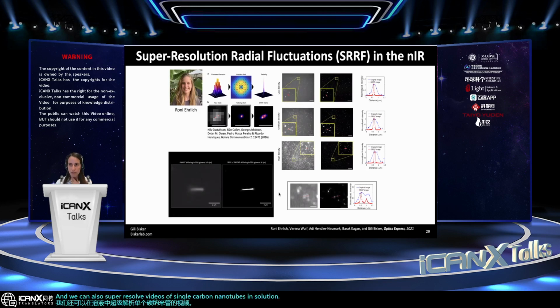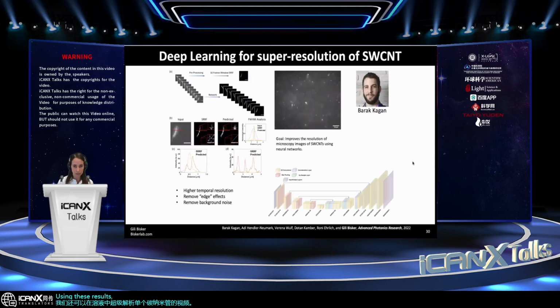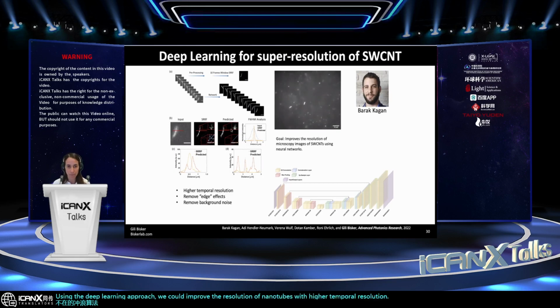Using these results, we then adopted a deep learning approach with a convolutional neural network architecture with the SRRF images used as the ground truth to super resolve images in real time, compared to the SRRF algorithm, which is not in real time. Using the deep learning approach, we could improve the resolution of nanotubes with higher temporal resolution. We could remove the edge effect, as you can see here, and we could remove the background noise compared to the SRRF results.